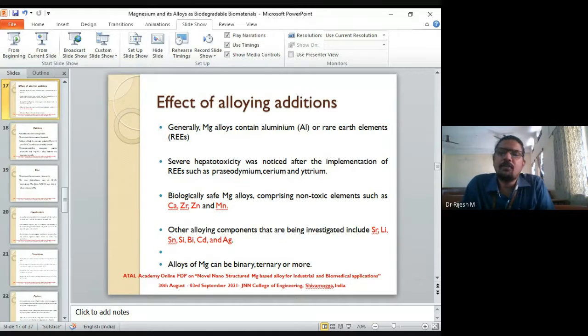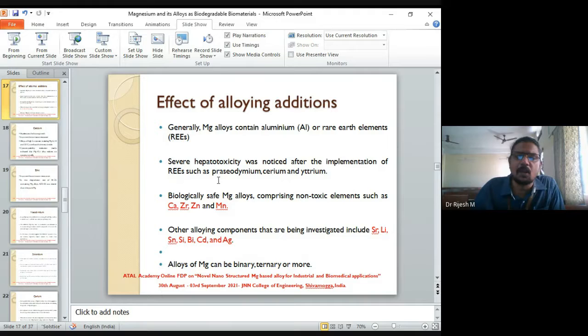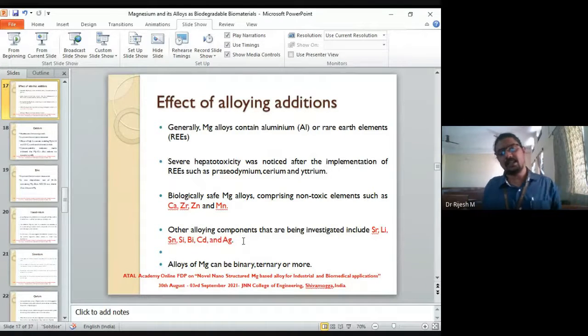We were discussing that pure magnesium is not feasible as a biodegradable biomaterial because it corrodes too quickly. So we have to add something to this magnesium so that it decreases the corrosion rate. The major alloying additions for magnesium are aluminum or rare earth elements. Severe hepatotoxicity was noticed after the implantation of rare earth metals such as cerium, yttrium, etc. The biologically safe magnesium alloys generally have alloying additions like calcium, zirconium, zinc, and manganese. The other alloying additions are strontium, lithium, cadmium, silver, etc.